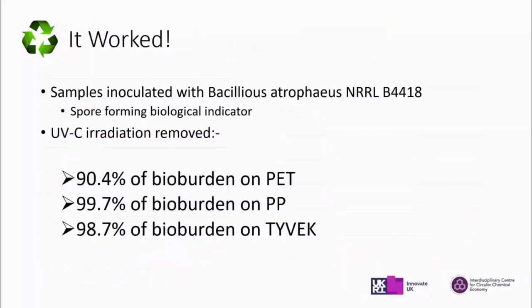So samples inoculated with a spore-forming biological indicator were tested across a range of exposures, and we found that rigid PP and PET evidenced a kill rate of 99.7 and 90.4% of colony-forming units, respectively, and Tyvek film performed a kill rate of 98.7%. Also, the natural characteristics such as the bacteriostatic nature of PET and the optical properties of PP have evidenced that these should be treated independently to optimise sterilisation results and maintain integrity.